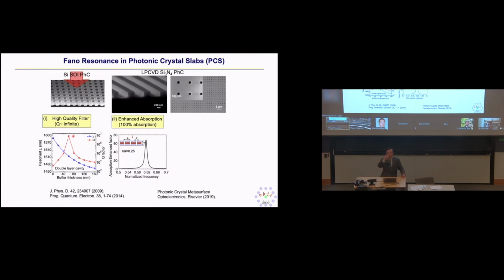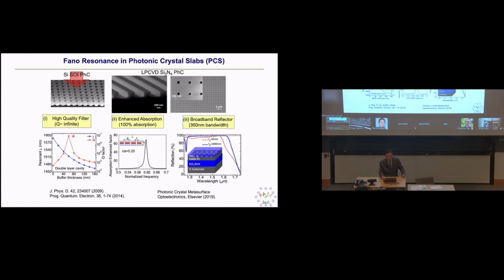The idea is if you have a very thin absorption layer, you can design it so that thin layer gets 100% absorption, I will show one slide, and otherwise only 50% absorption, by the so-called critical coupling concept. And you can look into broadband reflectors to replace the DBRs in the VCSEL structure we're using now, which is a multi-layer stacked dielectric structure. Now you can make this broadband reflector from a single-layer lattice.